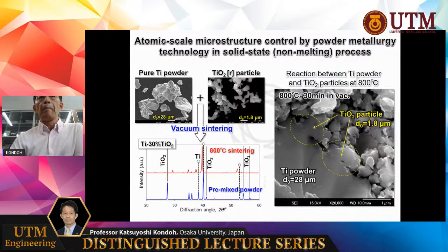By mixing the two powders, pressing and sintering in vacuum conditions, this TiO2 completely dissolves and oxygen atoms diffuse into titanium. And we obtain titanium materials with uniform distribution of oxygen atoms. For example, on the right side, I show the SEM photos, just after sintering at 800 degrees C.